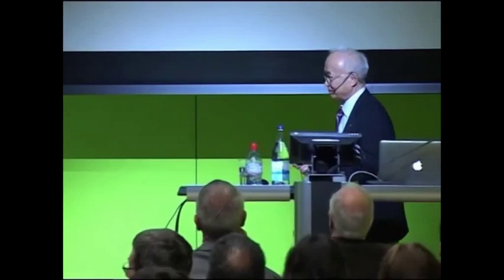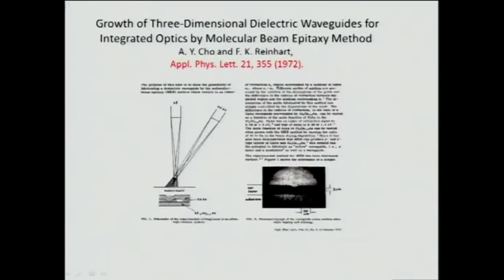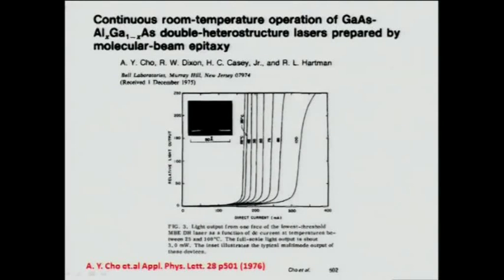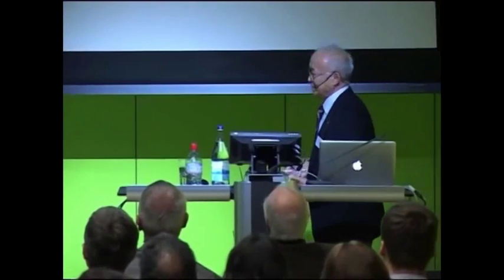And then, of course, I just take one of the many papers I collaborated on with Franz, showing the growth of 3-dimensional dielectric waveguides for integrated optics with molecular beam epitaxy in 1972. With the mask growth, we grew a core of gallium arsenide surrounded by aluminum gallium arsenide, as integrated optics waveguides grown in the layer. I continued to work hard, trying to make the grown material have fewer traps and fewer impurities in the aluminum gallium arsenide layers, continuously looking at how to make the system cleaner.